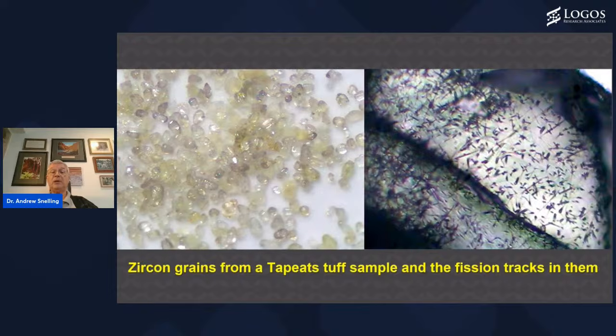What does this mean? Well, we know again that if there had been elevated temperatures in the Tapeats sandstone, these fission tracks, where the uranium atoms split due to fission, would have been annealed or obliterated. In other words, the damage to the crystalline structure, the heat would have caused the crystals, the atoms, to vibrate sufficiently that they would regroup back into the pristine condition of the zircon grains and the quartz grains. They would have been obliterated.